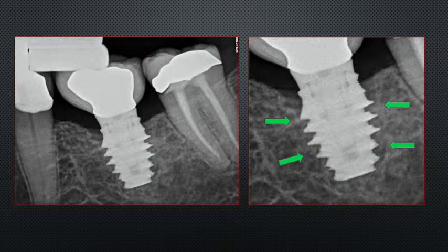If we enlarge this for a moment, you're going to see something quite dramatic. The density of the bone where there was a gap is actually better than the bone that is distant from the implant, which means that the combination of the LPRF and the release of calcium from that calcium phosphate surface had a synergy and enabled me to get what was essentially a failed implant that was then loaded and put back into function.